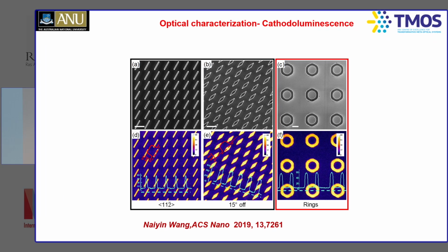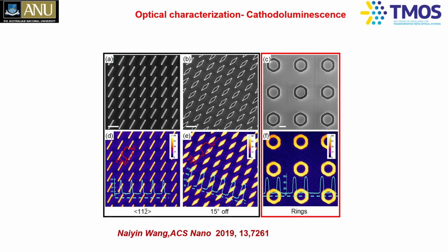And Naiyin Wang has taken these nanomembranes, nano diamonds, and nano rings, and then looked at the cathodoluminescence. Instead of using photoluminescence, cathodoluminescence gives you much higher resolution, essentially exciting these nanostructures with an electron beam in a scanning electron microscope, creating electron hole pairs, and looking at the light emission. You can see that you can get excellent uniform light emission, indicating that the hard work of 3 years of Naiyin Wang really paid off. And then these types of structures are very useful for making optoelectronic devices. Particularly, I'll come back and share with you ring resonator lasers based on this bottom-up approach, indium phosphide nano rings.